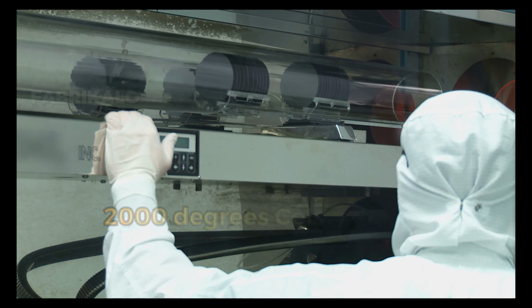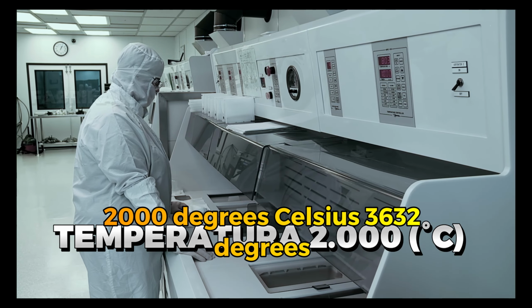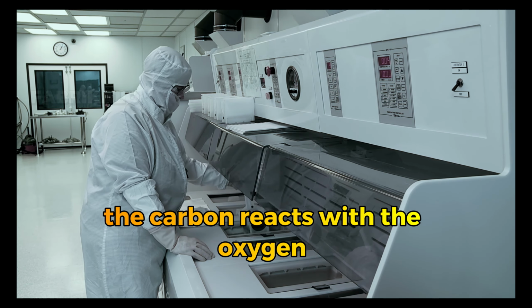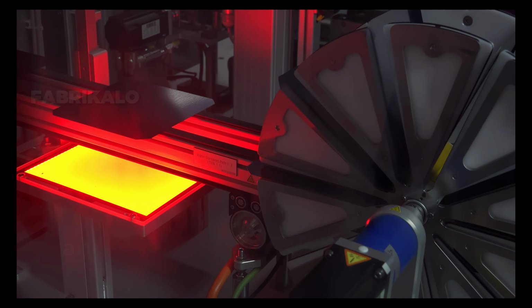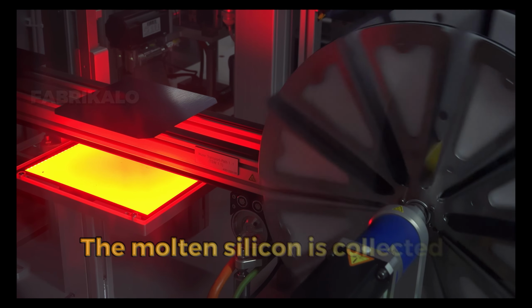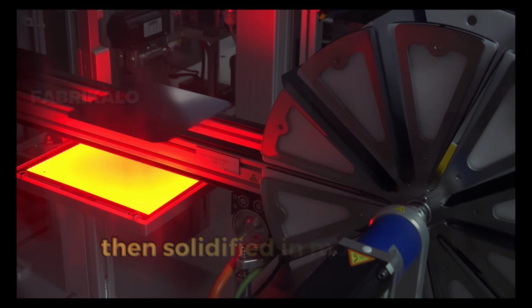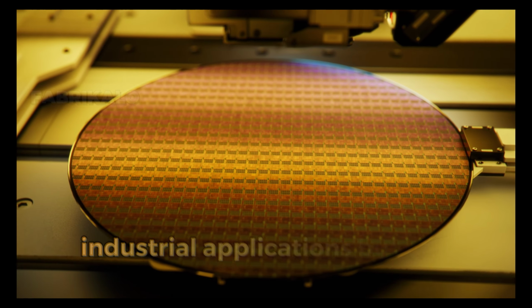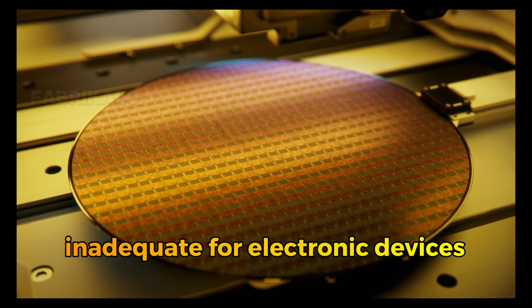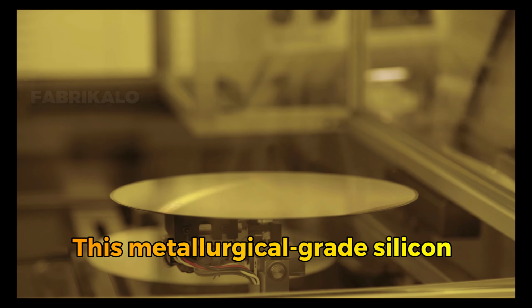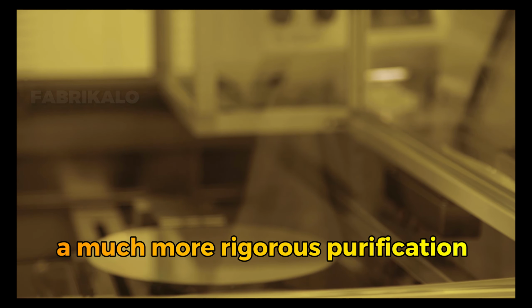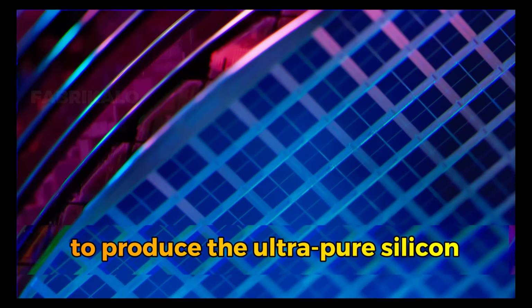When temperatures reach around 2000 degrees Celsius (3632 degrees Fahrenheit), the carbon reacts with the oxygen in the quartz, producing carbon monoxide, CO, and leaving behind molten silicon. The molten silicon is collected at the base of the furnace and then solidified in molds for transport. At this stage, the silicon has a purity of around 98 to 99%, which is sufficient for general industrial applications but still inadequate for electronic devices or solar panels. This metallurgical-grade silicon serves as the foundation for a much more rigorous purification stage later on. Converting quartz into metallic silicon is energy-intensive, but it is absolutely essential to produce the ultra-pure silicon required by the